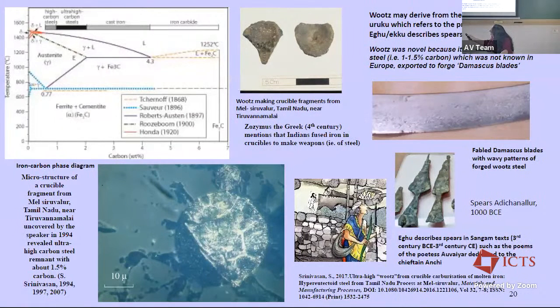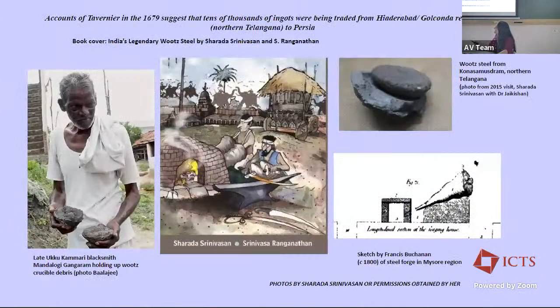It has gone into temperatures of at least about 1200 to 1300 degrees under very reducing conditions for this remnant austenite to be formed. So it tells you that, and even the globular structure tells you that it was practically molten. So the fact that they were able to achieve this kind of molten carburization is very significant, as a high temperature process which was difficult to achieve in antiquity.